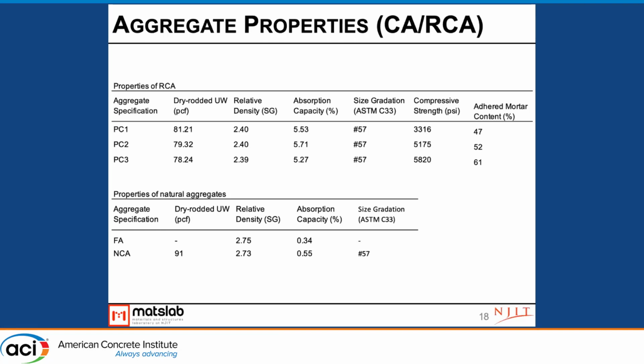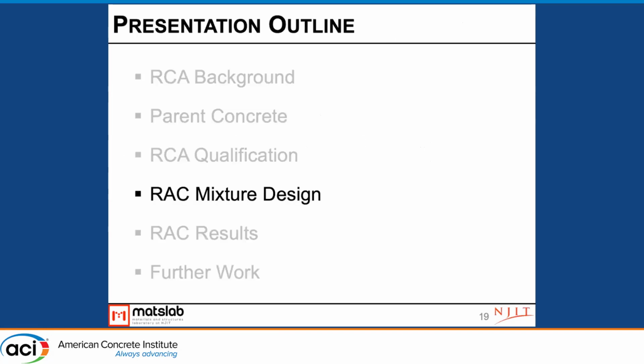So again, as you can see, our size gradation is the same across the board. For our parent concretes, we achieved a number 57. And for our natural coarse aggregate, we also have a number 57 aggregate in the lab. That natural coarse aggregate was used in everything. So to make the RCA, or the parent concrete that was then made into RCA, it was the same coarse aggregate stock. What we're trying to do is keep as many variables constant as possible so that we can see the effects on the recycled aggregate concrete. I also want to point out the adhered mortar contents. As the strength of the RCA system increases, the adhered mortar contents go up, which makes sense if you think about the ACI mixture design process.